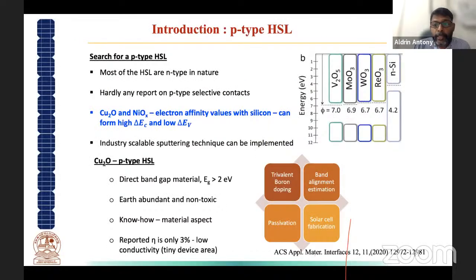And this is what we have done. We chose this boron doped copper oxide as a hole transporting layer, and it has a band gap of around 2 electron volts. So it allows all the other energy radiation to pass into the solar cell. Copper oxide and nickel oxide are basically two materials which show p-type conductivity, and whose electron affinity values can match with silicon to form a hole selective nature. They have a high delta EC and a very low delta EV, that is the band offsets for electrons and holes.